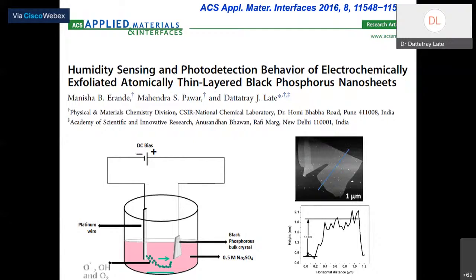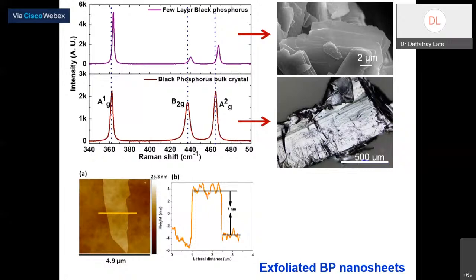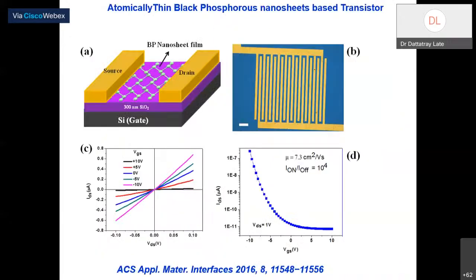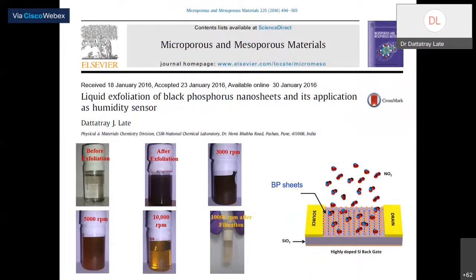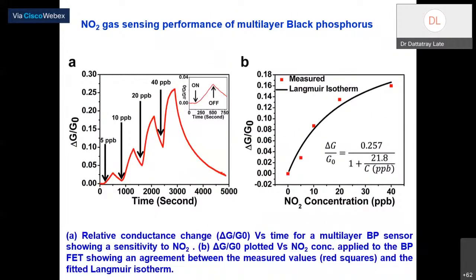We have solvent as Na2SO4, and then we have of course applied the voltage between these two electrodes. We will be able to exfoliate this black phosphorus into this particular solvent. You can separate it out, and you can have layer thickness and other characteristics done on this material. You can see Raman spectroscopy, AFM, and of course we have fabricated a transistor based sensor device based on this material, and again also done liquid exfoliation of the same material, and also used for gas sensing application.